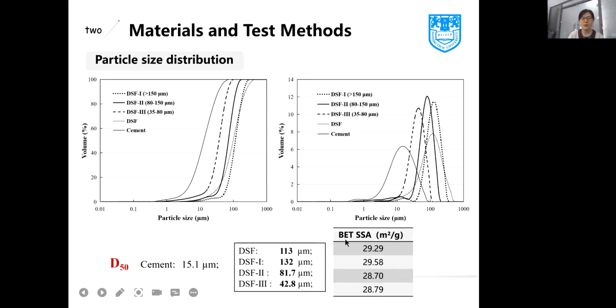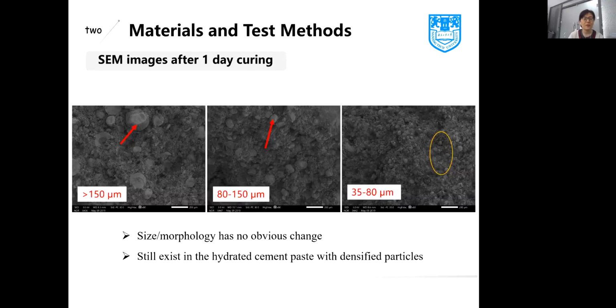It's interesting, we also did the BET specific surface area. The change of the fineness of densified silica fume has no influence on the BET specific surface area. It's around 30. We also studied the SEM image. You can see the size or the morphology of densified silica fume has no obvious change after 1 day of curing. It still exists in the hydrated cement paste as densified particles.